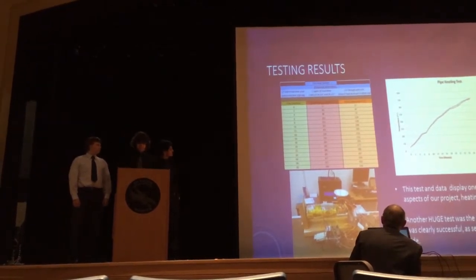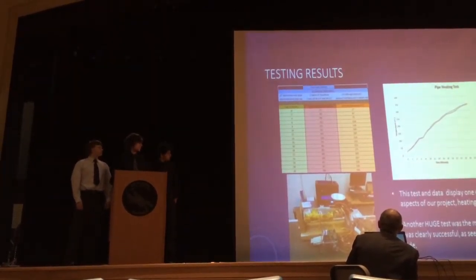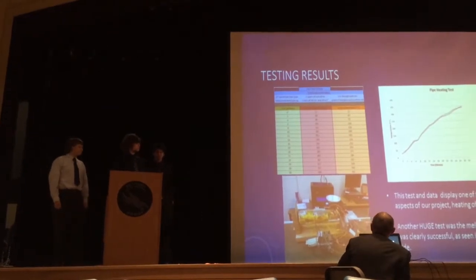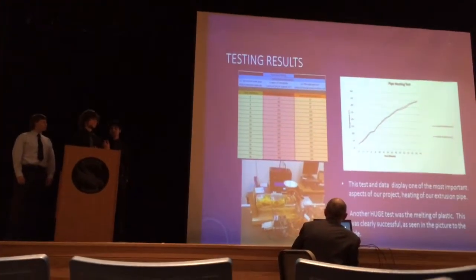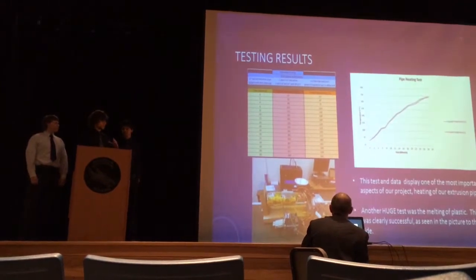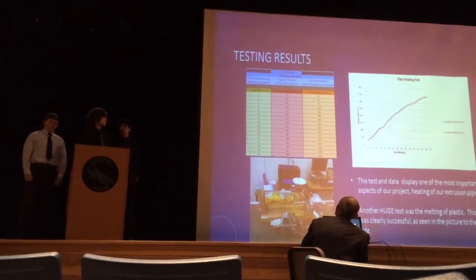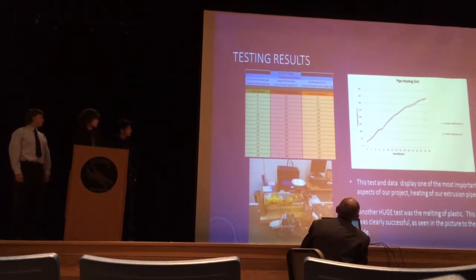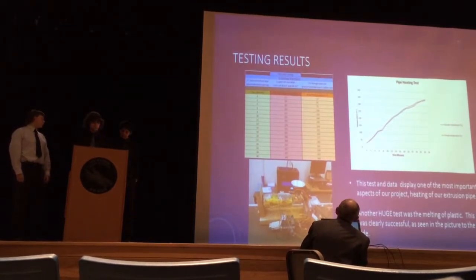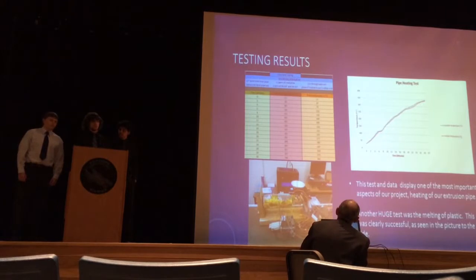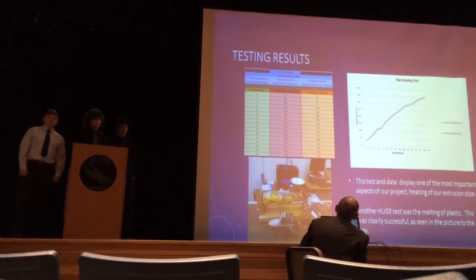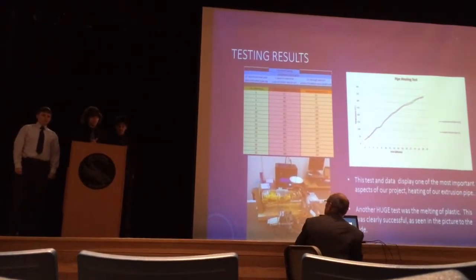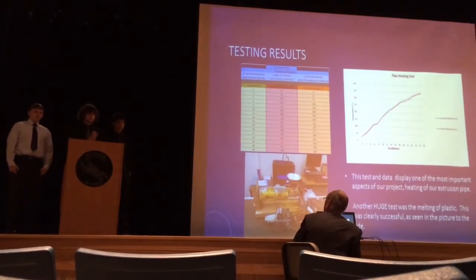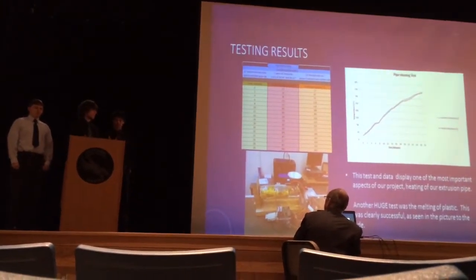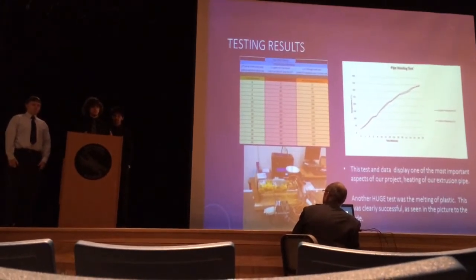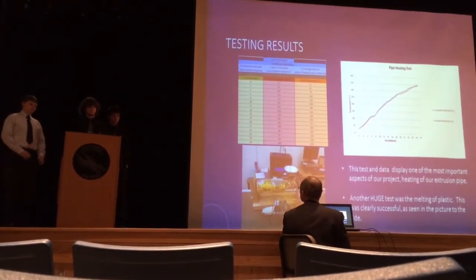Now, for testing of what we tried to do here, there were two big tests. There was the testing of heating, which is in that table right there. And what we did is we wanted to conquer the problem of measuring our temperature, because the biggest thing was, where were we going to put our temperature probe? Because for a long time, we thought that the only place that we could place it was on the inside of our tube, and that caused a lot of problems.